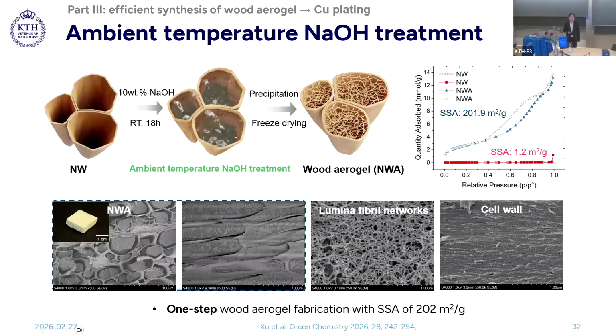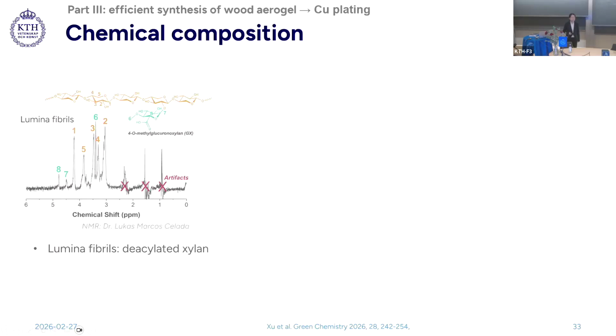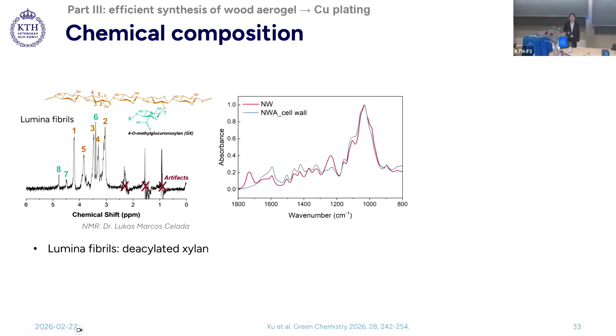To get a better understanding of this aerogel structure, we isolated lumina fibril networks from wood templates and analyzed their chemical composition. The diffusion edited NMR of lumina fibrils reveals the predominance of deacetylated xylan. From the FTIR spectrum, the bands associated with acetyl groups in xylan are present in the cell wall of native wood, but absent in the cell wall of wood aerogel. This absence confirms the migration of xylan from the cell wall to the lumen.